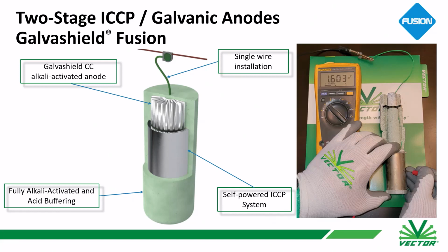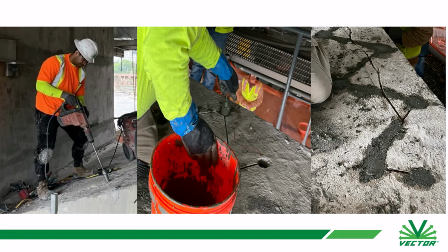They basically have a battery incorporated in with the galvanic anode, so it gets you a higher amount of current to begin with, and they're usually designed for 20 or 30 years of protection. You see them being installed proactively into drilled holes. This is a connection to the embedded steel, and then you have a header wire that kind of interconnects the anodes, and there's a spec for how many anodes you can put per rebar connection or steel connection.